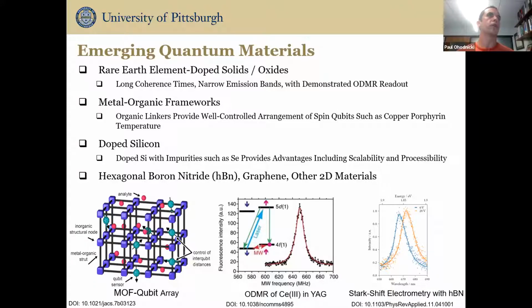And then for materials that are a little bit further out on the horizon but very interesting, these would include rare earth doped solids, where you can use characteristic energy states of the f and the d electrons in things like optically derived magnetic resonance, and some of that's been demonstrated for materials such as cerium in YAG-based crystals. Metal organic frameworks are a very interesting class of materials. One of the reasons is that there's so much flexibility and control over how we place various atoms and various ions within a metal organic framework because of the fact that it's this hybrid organic and inorganic structure. In addition to introducing controlled qubits, we also could have the potential for introducing controlled spacing between qubits and understanding interactions between qubits. So we are using metal organic framework materials currently with some of these sensing platforms, and moving forward, this may be an interesting direction to go as well.